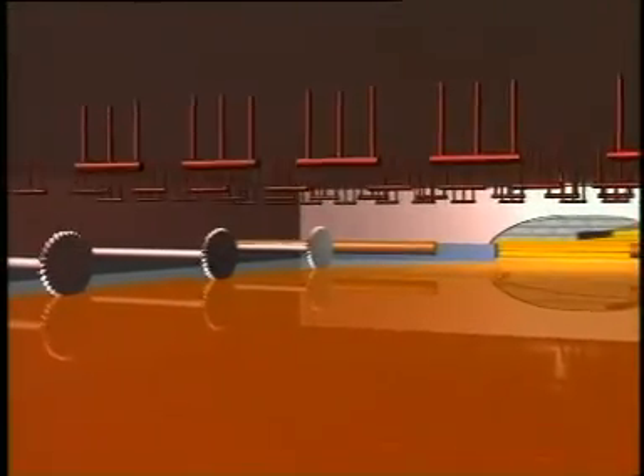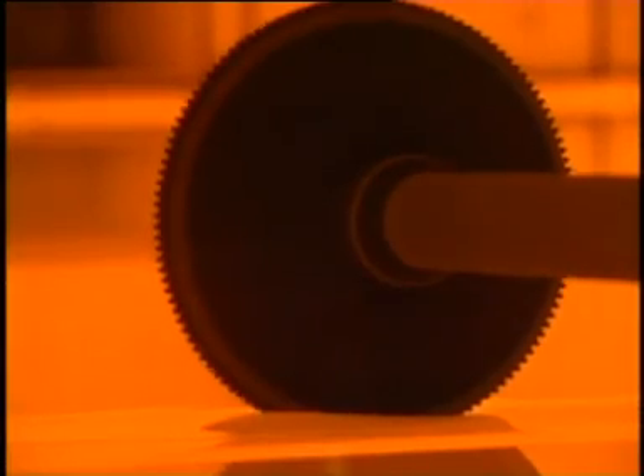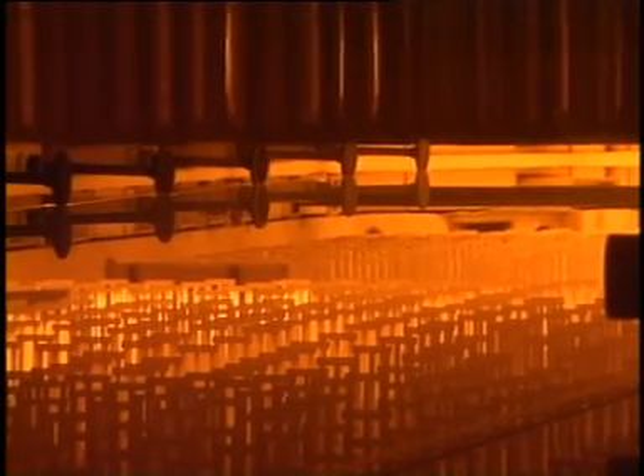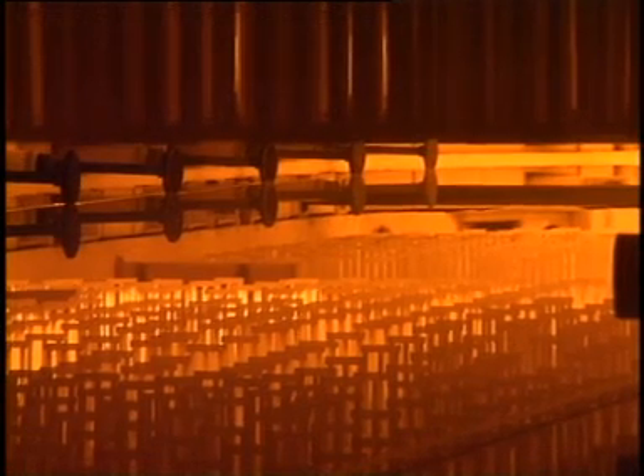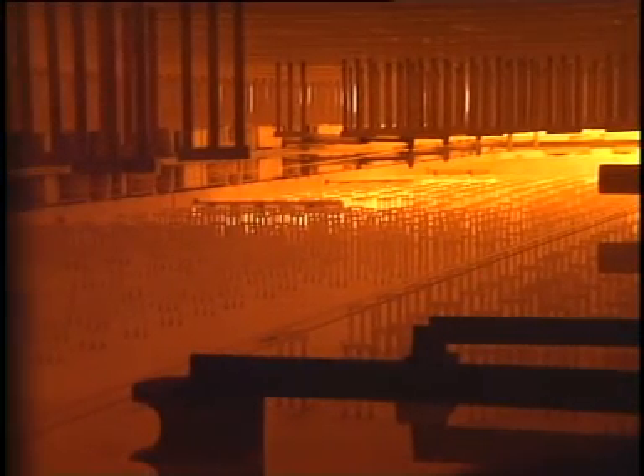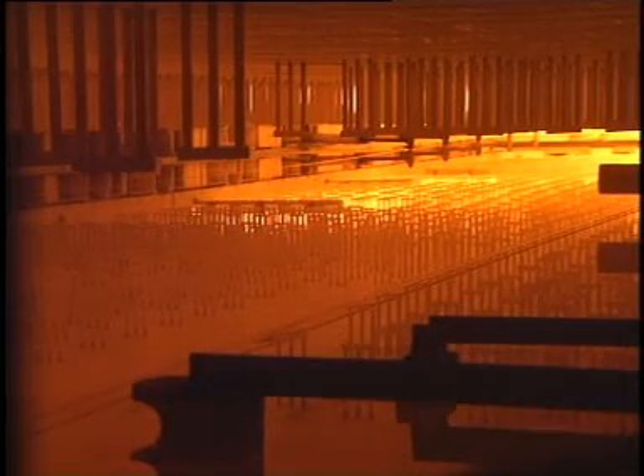The glass is made thicker by confining its initial outward spread over the tin. To make thinner glass, the top rollers controlling the width of the glass are speeded up to produce a gentle stretching action. A controlled atmosphere of hydrogen and nitrogen within the bath prevents the tin from oxidizing. When it emerges from the tin bath, the glass is sufficiently hard not to be marked by the conveyor rollers.